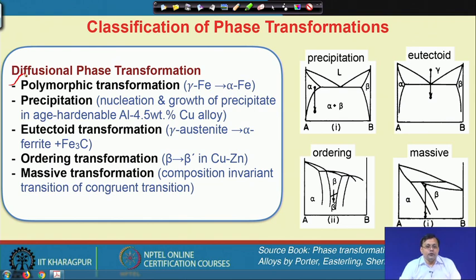And now, if we cool it down, then the gamma iron will transform into alpha iron, and this requires nucleation of alpha iron in the gamma iron boundaries, because this is a solid transformation, and here the growth of those alpha iron nuclei will occur during cooling of gamma iron. So, this is a polymorphic transformation, where there is no compositional change.